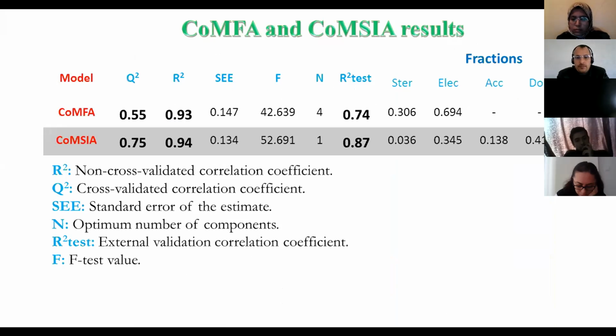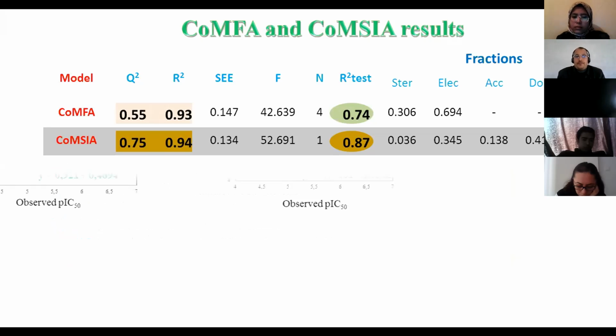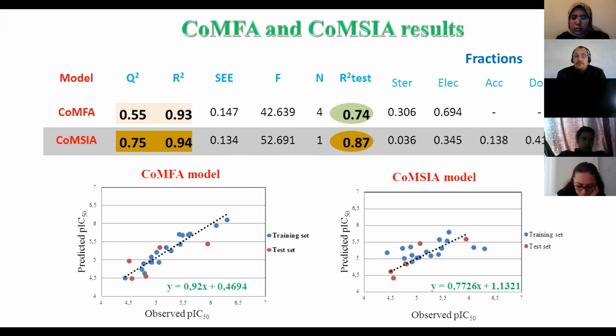The second table gives the statistical values of CoMFA and CoMSIA. As you see from this table, the values of R square and Q square are very important. The table also shows that the R square test values of CoMFA and CoMSIA are greater than 0.66, which implies that our model has been well validated. From figure 3, the good linear relationship shows that the activity predicted by the derived models agrees with the experimental data, indicating that these models had satisfactory predictive power.